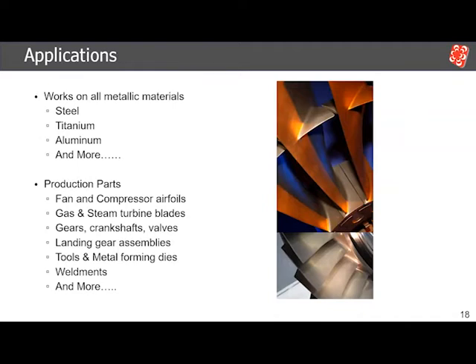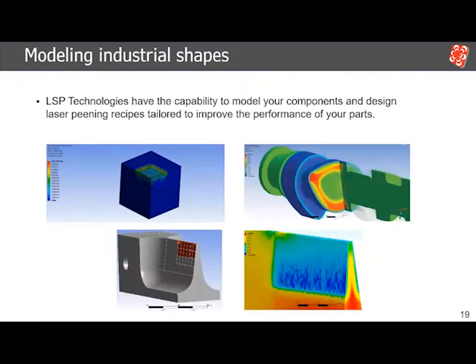So with that being said, we have the ability to model the laser peening process of these components. When a customer brings in any part that they are facing failures on, or that needs fatigue enhancement or life enhancement in general, we can take that 3D model and apply laser peening process modeling on top of it. Again, Stan tomorrow at 1 p.m. is going to explain more about our ability to model different parts, and we can predict the residual stresses that come out of the laser peening process, and we can estimate how much life improvement comes from the laser peening process.